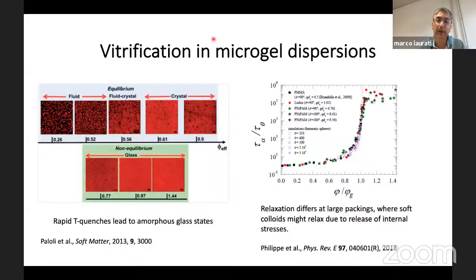For example, it has been studied in this work from the group of Peter Schurtenberger, where actually they used temperature changes to induce the glass transition. So essentially, starting from the deswollen state, if you rapidly quench the system to smaller temperatures, of course, you induce a change in the radius, and this change can lead to the dynamic arrest corresponding, of course, to the increase of the actual packing fraction. So they were able to see these glass states.